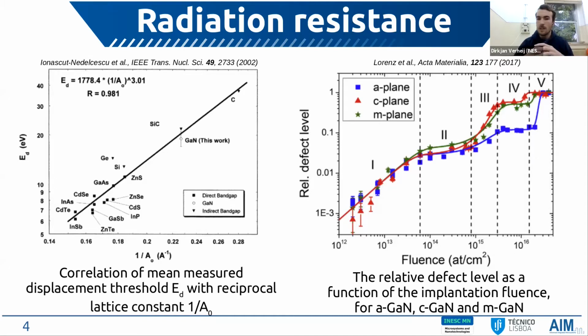Like I said, gallium nitride has a high defect mobility at room temperature, and this defect mobility basically causes recombination of the created defects, and this then stabilizes the creation of defects. This effect is called dynamic annealing, and materials that have a strong dynamic annealing effect typically also present a higher radiation resistance.